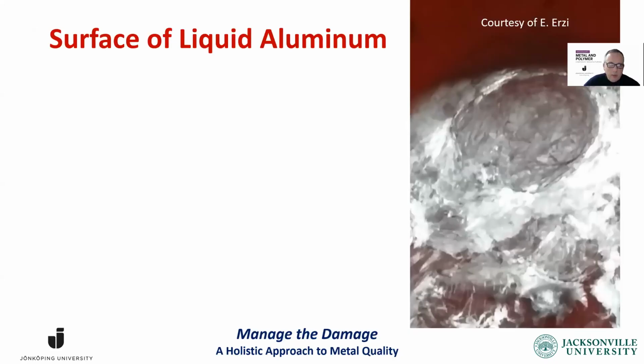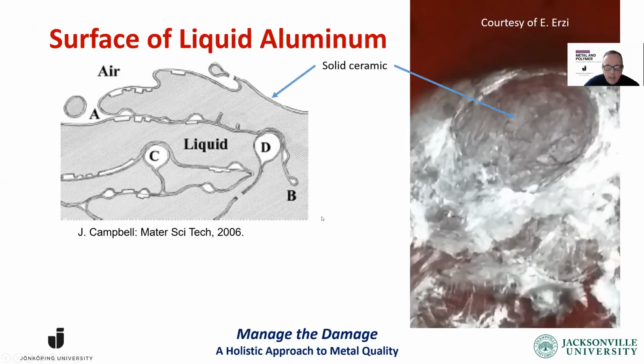The surface of the liquid aluminum, however, is not covered by liquid aluminum. It's covered by a solid ceramic, and most of the time it's alumina. And when we treat liquid aluminum, just like we treat water, that's where the problems start. Because as long as the surface oxide remains on the surface, we don't have any problems. It's a protective layer, it's good, no worries. But when it gets entrained, because we disrupt the surface of liquid aluminum, that's where the problems start.